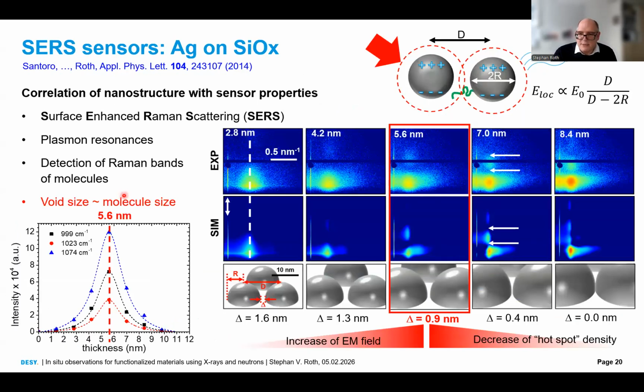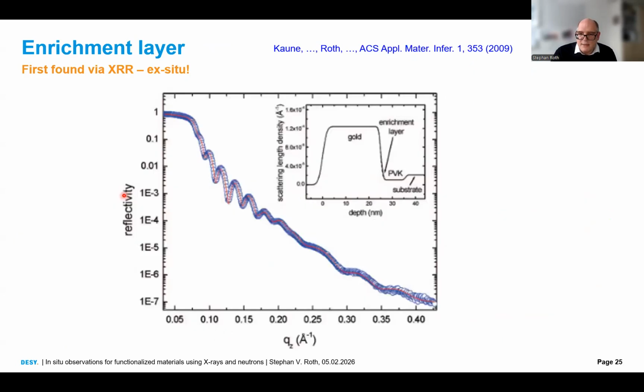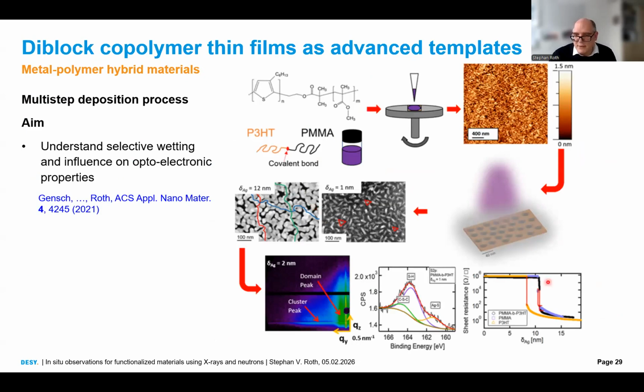Let me just jump a little bit here. When we look into this here, into the percolation threshold, what we always do is we measure the electrical conductivity or the onset of electrical conductivity. Then we calculate this 2R over D value. And if this is 1, we expect electrical conductivity. And if it's later or earlier than what we measure with a voltmeter, we know that the clusters are either more cylindrical or more flat. So we need to apply a correction factor.